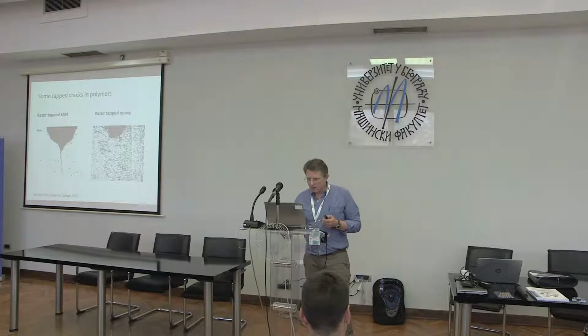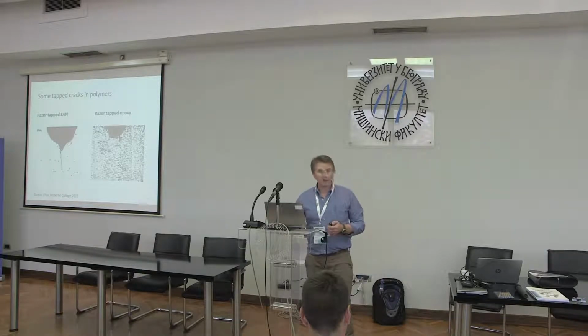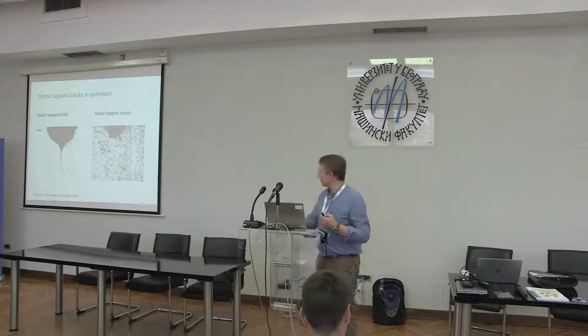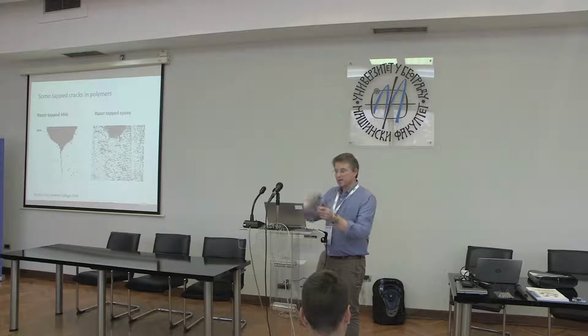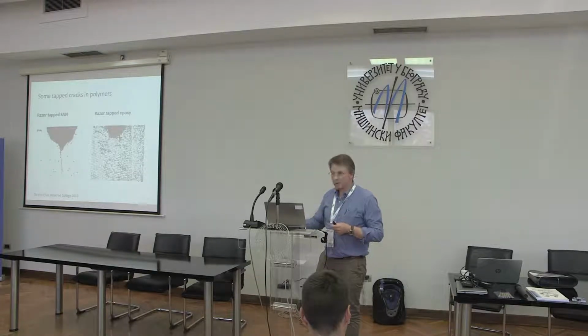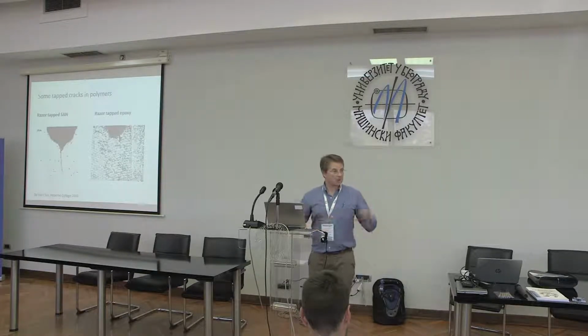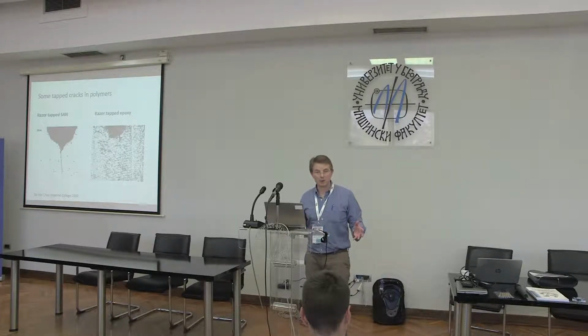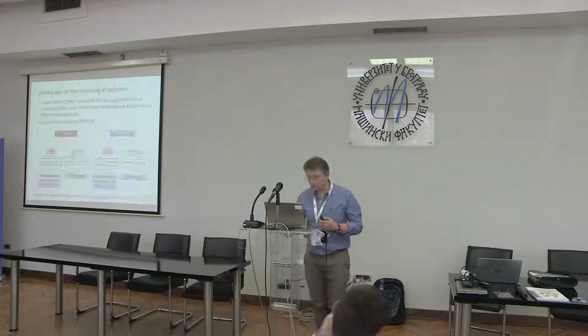So that's an issue there. And what happens for all the materials that we can't do this to? So these materials that are tougher, under the conditions that we're investigating, we simply tap on the crack and nothing happens. So it's unsatisfactory, and this was becoming increasingly apparent as people were testing a wider range of polymer materials. The methodology was fine, but you couldn't get the cracks into the material in the first place.